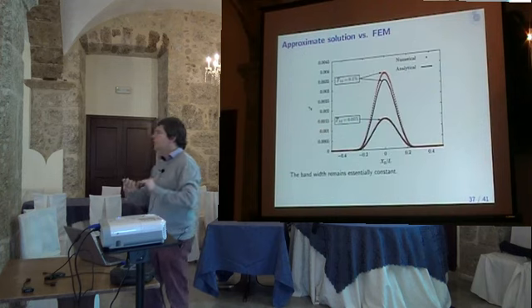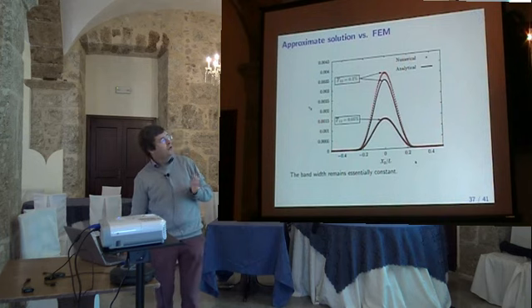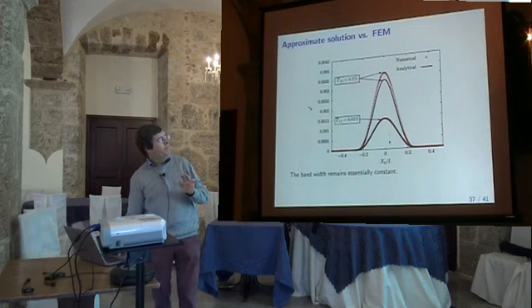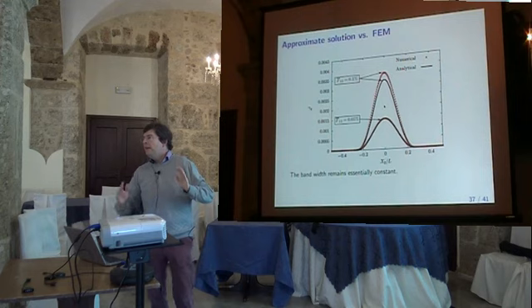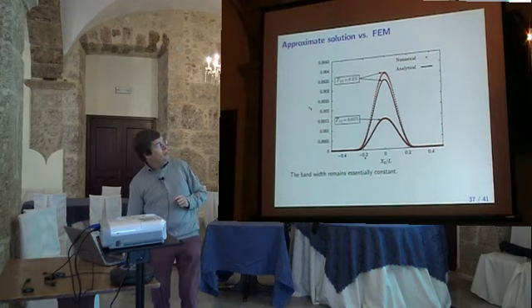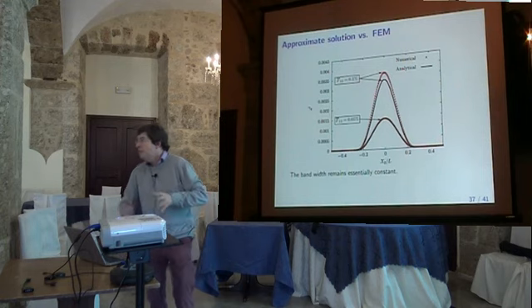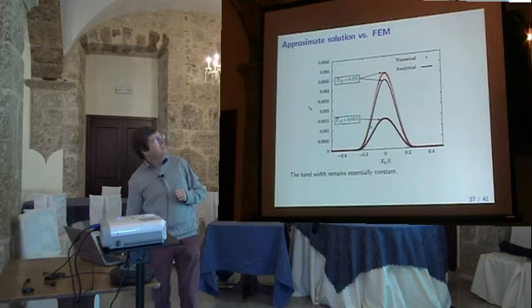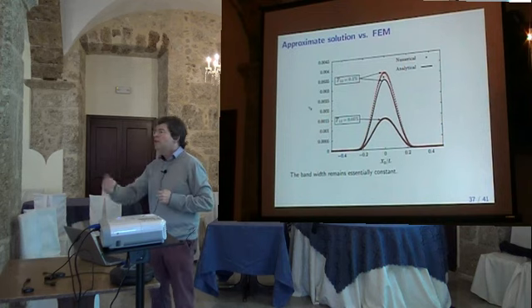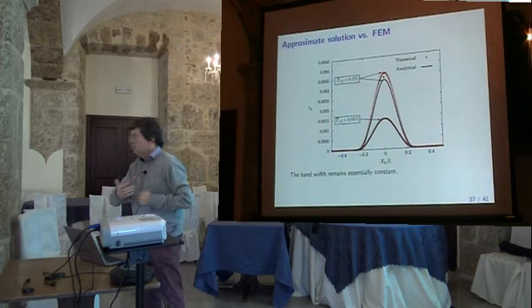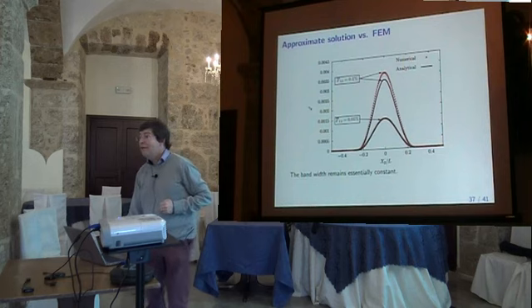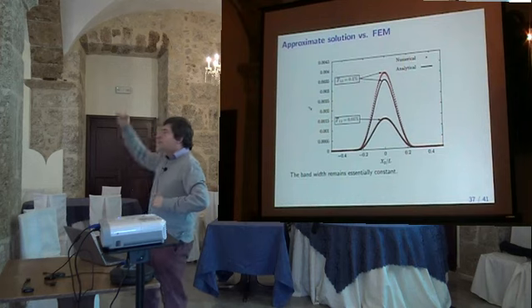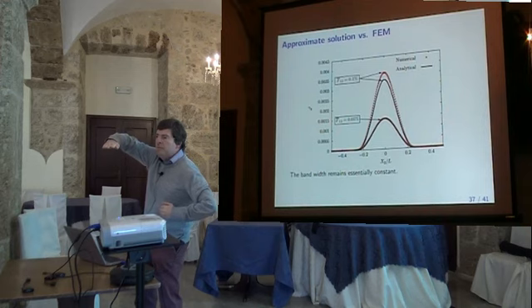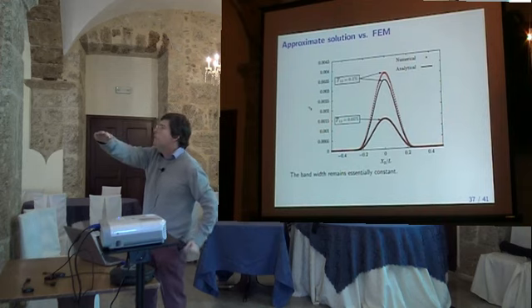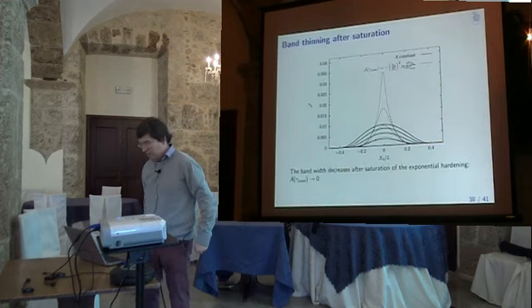This is a result. If you have not much deformation, the solution is perfect. And if you increase the strain, you have still localization. You see the bandwidth remains the same. We have no broadening. But the analytical solution is not exact anymore. So this is finite element simulation. And what happens after? What happens after? Because this is during the exponential drop. But what happens when you reach the plateau, in fact? And this is what happens.